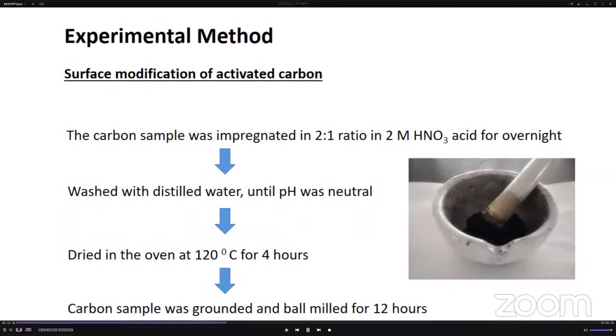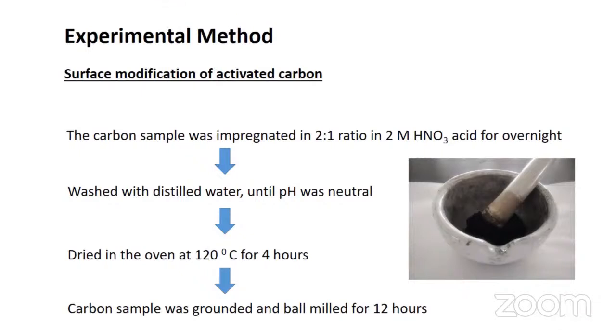Under the experimental method, we are going to discuss the surface modification of activated carbon and fabrication of the electrode. First, we talk about the surface modification of activated carbon. The carbon sample was impregnated in 2:1 ratio in nitric acid overnight, then washed with distilled water until the pH was neutral. Dried in the oven at 120 Celsius for 4 hours. After that, the carbon sample was ground and ball milled for 12 hours.